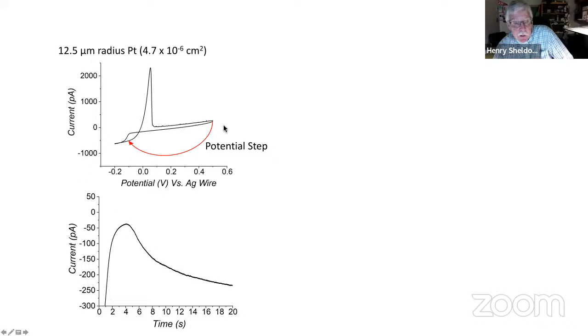And if you do the experiment twice, you get essentially the same curve. And if you do it 100 times, you get essentially the same curve each time, all right? And you can model this. There are differential equations or expressions that take into account the kinetics of nucleation and the diffusion of the silver ions. The equations are just horrendous, but there are equations that will allow you to model this response function, all right? And they're all deterministic type equations.